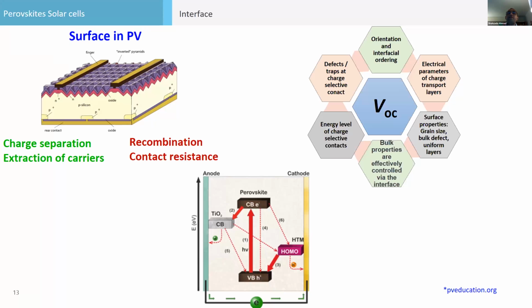Energy level of the charge selective contact matters, because perovskite is sandwiched between an N-type conductor and a P-type conductor, and both should be very well aligned. Energetically, they should be favorable to inject the charge in a facile manner. Otherwise, they will not be energetically aligned, and we will have a loss at the interfaces. Bulk properties are effectively controlled by the interface. The type of the crystal and the size of the crystals contribute a lot to the open circuit voltage, and surface passivation passivates the grain boundaries, or we make the crystal larger to minimize the grain boundaries. In this way, we will minimize defects and have a higher VOC.